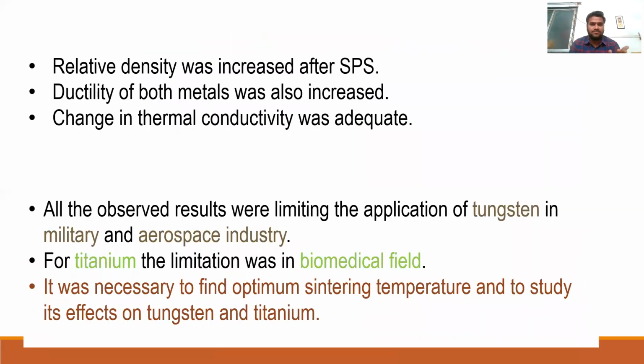The relative density was increased after SPS. Ductility of both the metals was also increased. The only positive thing was that the thermal conductivity was adequate. Then all the observed results were limiting the application of tungsten in the military and aerospace industry, whereas for titanium, the limitation was in the biomedical field. So to tackle this problem, it was necessary to find an optimum sintering temperature and to study its effect on tungsten and titanium.